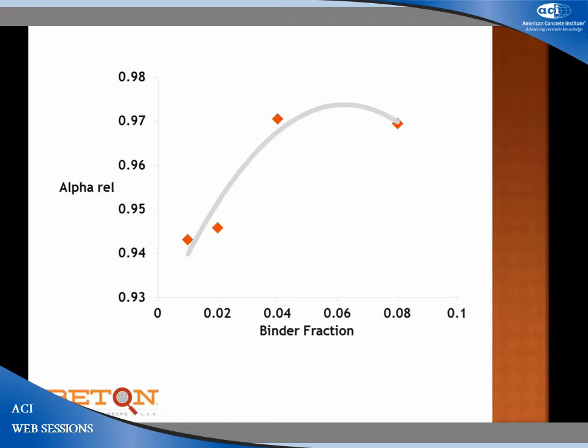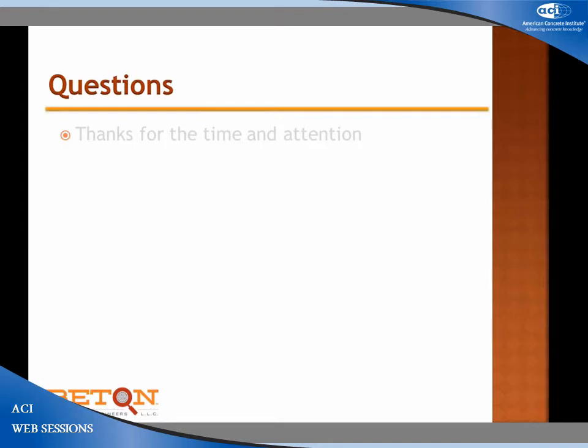But it is very useful, and it has led to many mixtures that use about 15% Portland cement, and about 500 or thereabouts pounds total cementitious material. If you put limestone in, David and I don't have the curve here to present, but you will see that increase come up to a point, and then it begins to decrease. Not necessarily telling you whether there's a reaction or not, but telling you that the addition of small quantities of limestone will give you higher degrees of hydration and therefore higher strength at a fixed amount of time. Whether that occurs from a physical or a chemical impact, it really doesn't matter from the point of view of designing mixes for engineering purposes.